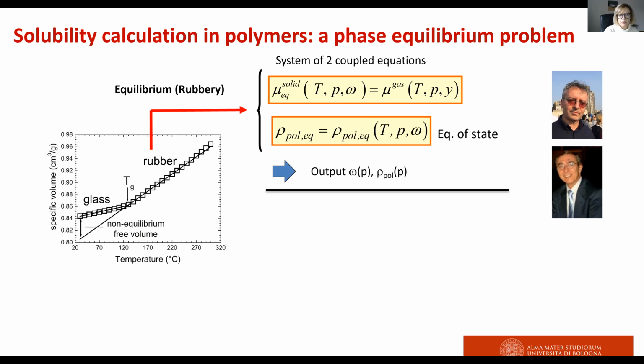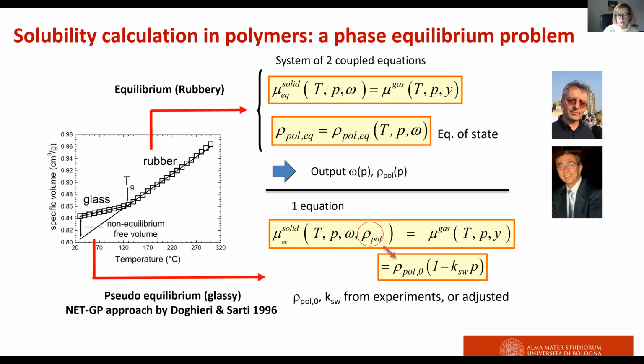If you're working below the glass transition, the equation of state can no longer be used, but you don't have to throw everything away, because you can still use your equation of state model to calculate the chemical potential of the gas absorbed in the glassy membrane according to the derivation provided in 1996, first with the NELF model and then with the more general NET-GP model.